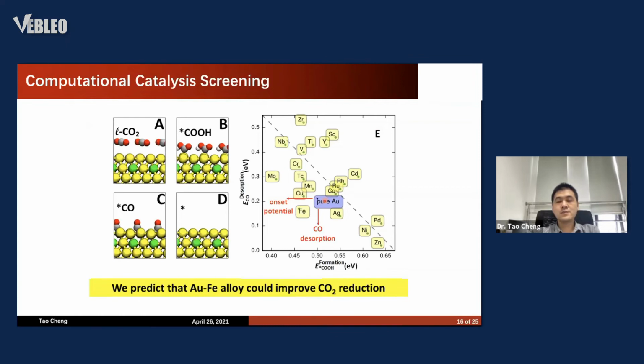Gold is pretty good at reducing CO2 to CO, but the performance is not perfect. What we are trying to do is think about whether it is possible to increase the performance of gold. The idea is that we can dope a second metal into gold. Then we can do this computational prediction to see which material gives us better performance than gold. Here we show that if you dope iron into gold, a small amount of iron into the gold, it should have better performance.